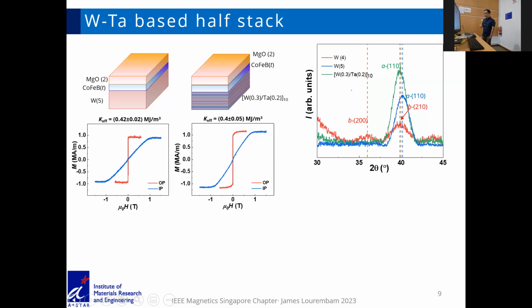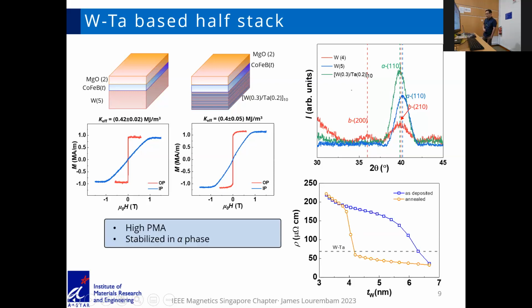To recollect, the beta phase has a higher spin Hall angle. And this can be observed in both XRD as well as the resistivity measurement. So low resistivity is for alpha phase, and high resistivity is for beta phase. Just a side note: the restriction of 4 nanometer thickness I mentioned is after annealing. If one anneals these samples, then the beta phase is lost above roughly 4 to 5 nanometers.